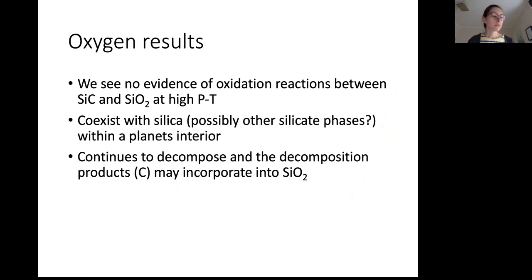Right, so results from these oxygen experiments, just to sum these up. Where we explored, we saw no evidence of oxidation between SiC and SiO2. Of course, if you explored other conditions, this might be different. So what we saw was that it can coexist with silica within a planet's interior at these pressure temperature conditions, but that it does continue to decompose, and that the decomposition products, mainly carbon, might be incorporating into silica.